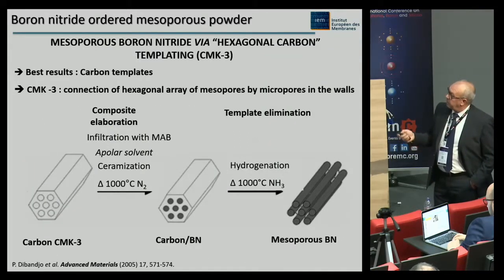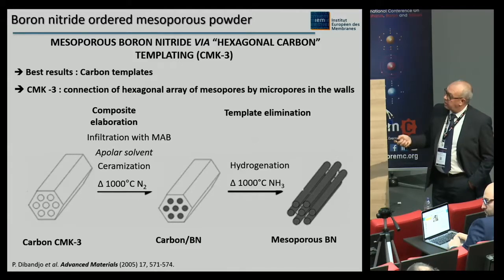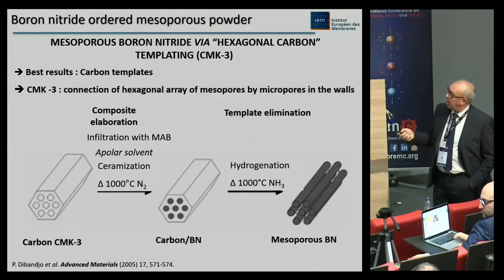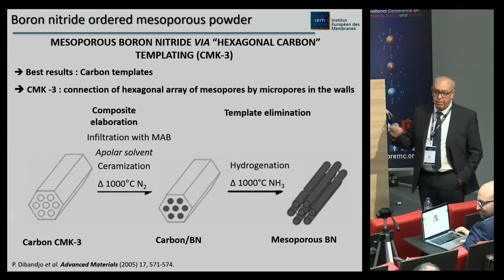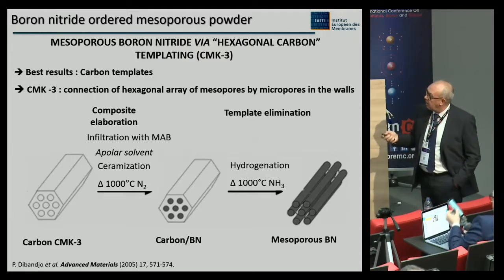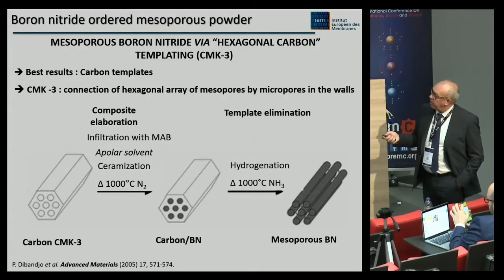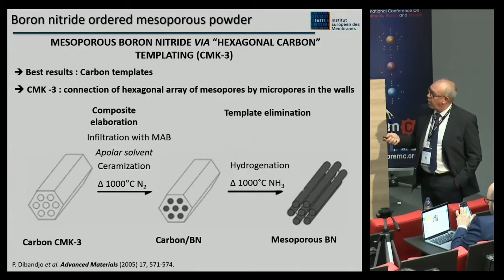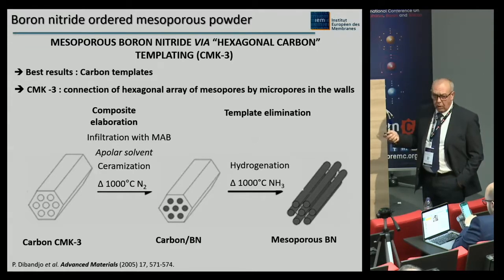Here, this is the example with CMK3 as template. We did that with the methyl aminoborazine, the precursor I showed you at the beginning. We treat this under nitrogen up to 1,000 degrees to obtain a composite carbon boron nitride, and at the end you have to remove the carbon by a reductive treatment under ammonia up to 1,000 degrees to obtain the replica structure of the starting compound. This is the idea, and here you can see the result.